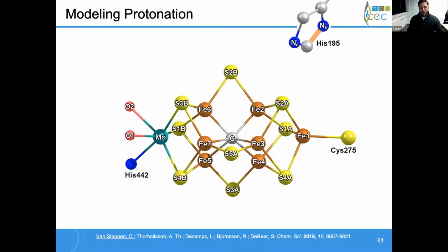Now, once we have our QMMM space decided, we can actually look at different models of what E1 might look like. So we go through all the different possibilities of the broken symmetry states between these iron centers when we add a single electron. And then we also look at different protonation sites for both the belt sulfide clusters, either subcubane. We also look at whether we have hydride formation, whether you can protonate the central carbide, as Per Siegbahn is a big fan of that one. And we also look at protonation state of, importantly, this neighboring histidine residue, 195, and on the homocitrate, which I haven't included here.